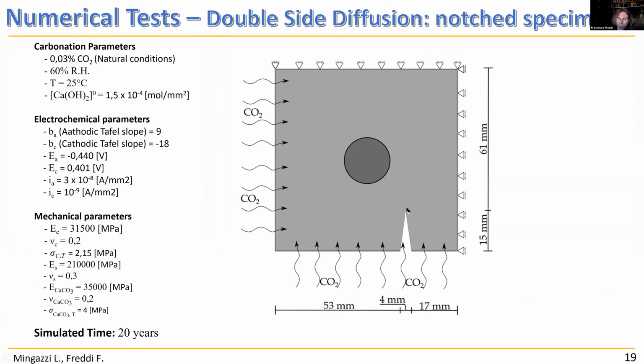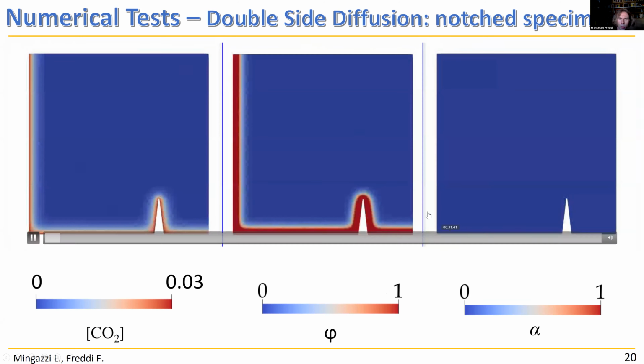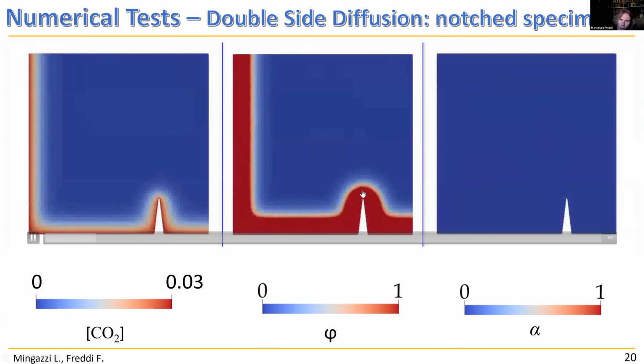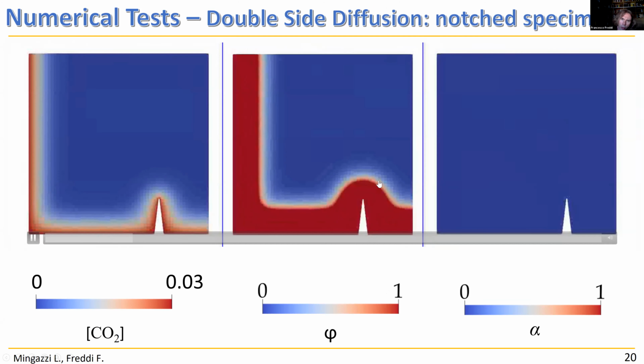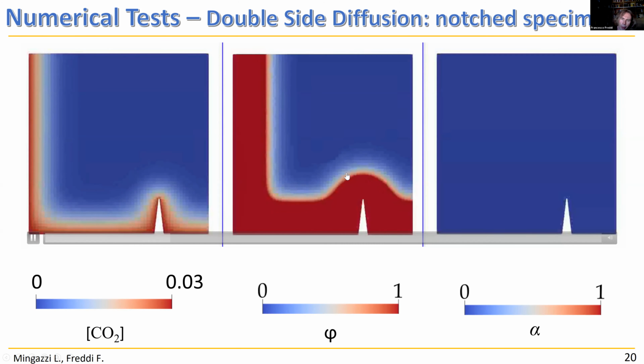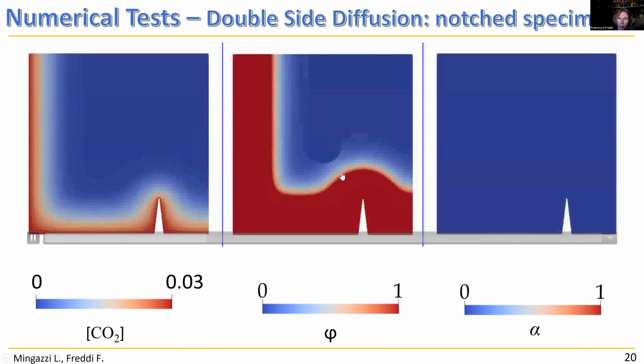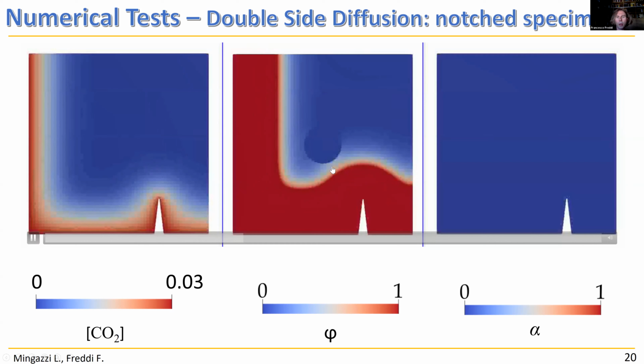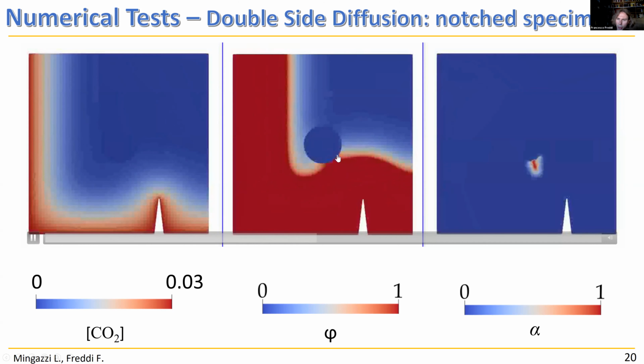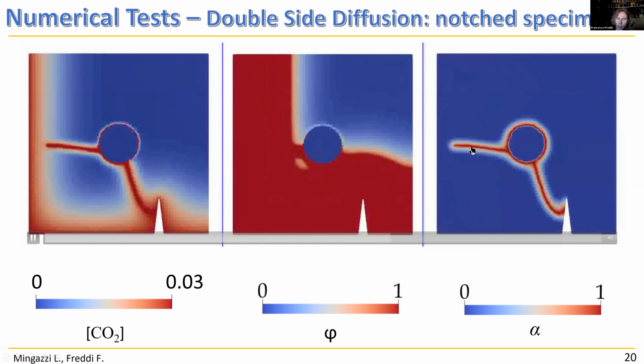I'm considering different boundary conditions in order to see if in some cases they may influence the result. So this is a very simple case. A small notch is considered along this horizontal border, and the solution is certainly influenced by the presence of these heterogeneities along the border. You can see that the carbonation front is deeper here, and the carbonation front reaches the bar starting from this notch, and the crack path is also influenced by the presence of this notch.